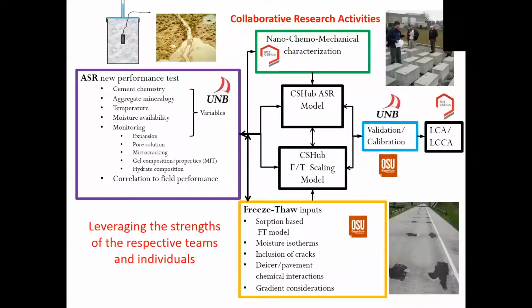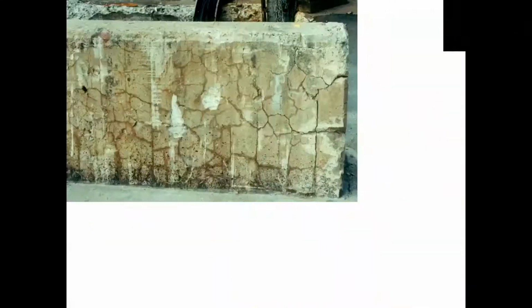And we've developed this data in the context of developing a new field performance test, or I should say laboratory test to simulate field performance. I know Jeremy asked me to introduce the phenomenon of ASR. So alkali-silica reaction, ASR, is a deterioration process that results in expansion and cracking of the concrete, which can, under certain circumstances, severely reduce the service life of the concrete.